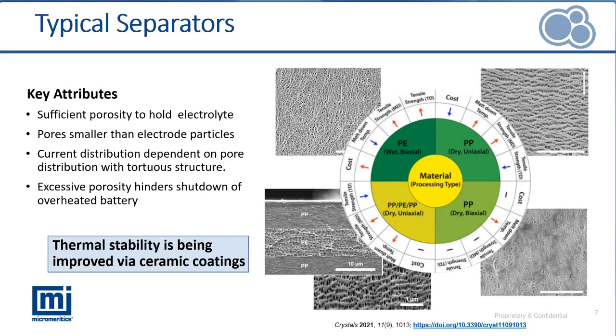No matter which separator you choose, it's important to measure the porosity, which is a key property. It's important to have enough porosity so you get the lithium ions moving through your separator. If you have too large pores, you're going to get the electrode materials touching and causing a short, which is a safety hazard. So you don't get dendrite formation, which again could be a safety hazard, you need a very uniform current distribution, which is important for the pore structure, uniform pore structure, as well as having a tortuous path through it. And then finally, if you have too much porosity, you're going to have the battery not shut down when you have an overheated battery situation.